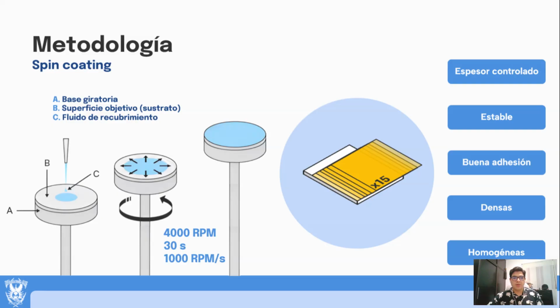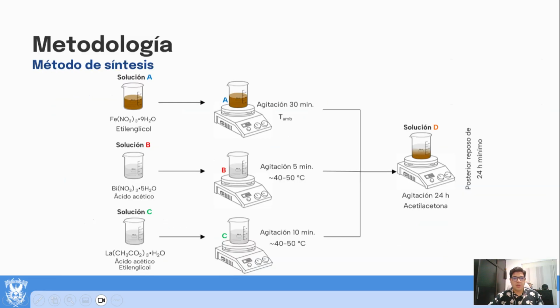The sol-gel method, followed by spin coating deposition, is widely used for fabricating these thin films due to its low cost, excellent stoichiometric control, and ability to produce homogeneous nanoscale coatings. The process begins with preparing a precursor solution typically containing bismuth nitrate pentahydrate, iron nitrate nonahydrate, and lanthanum acetate monohydrate as metal cation sources. These precursors are dissolved in a solvent mixture that may include glacial acetic acid and ethylene glycol, which act as stabilizers to prevent premature metal ion precipitation.